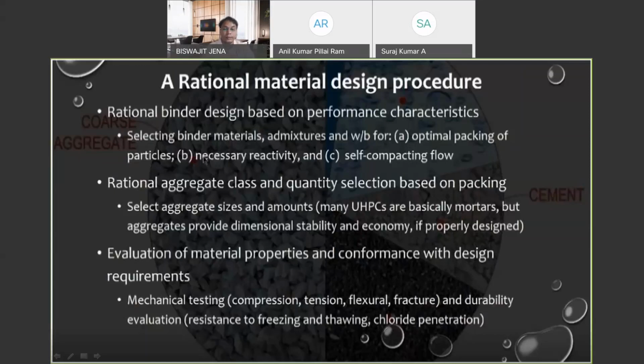In that case, the thing that comes to mind quickly is silica fume. So you have to now have materials that are smaller than 1 micron, which is silica fume. And also we can have metakaolin, which you can use if you need some aluminate effect in it. We have used both silica fume and metakaolin, and I will tell you why we have done that.